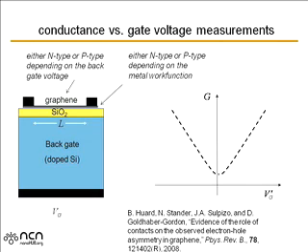You put the metal on the graphene, there's some charge balance, some charge transfer, either from the graphene to the metal or from the metal to the graphene. The net result will be that underneath that contact, the Fermi level is either above the Dirac point or below the Dirac point. So it's either N-type or P-type. So depending on what metal you've used, when you measure conductance and sweep the piece in between from N-type to P-type, you'll either be the same material as underneath your contact or you'll be opposite. So on one side, you'll see that reduced conductance of the p-n junction, and on the other side you won't.